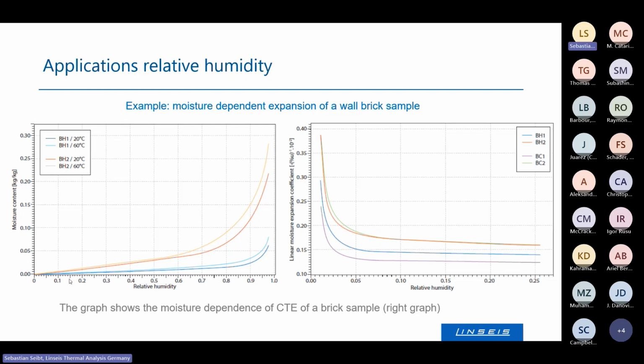It was placed on the balance and it was checked how much moisture came off. As you can see, the moisture uptake was quite slow up to a certain level of humidity. Then suddenly, no matter if it's hot or cold, no matter 20 or 60 degrees, the moisture uptake of the bricks increased.